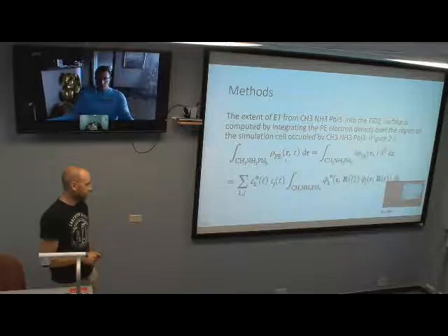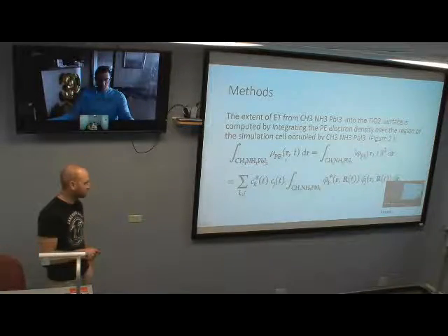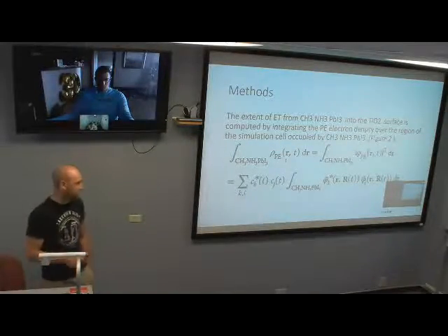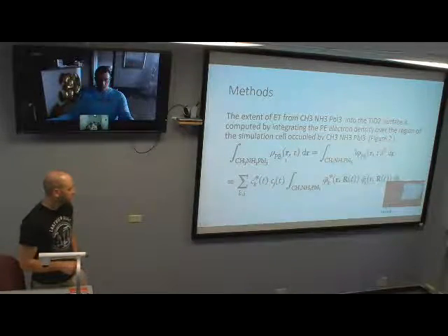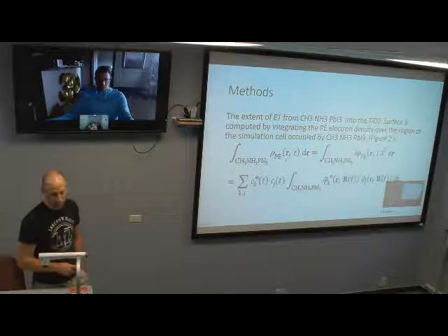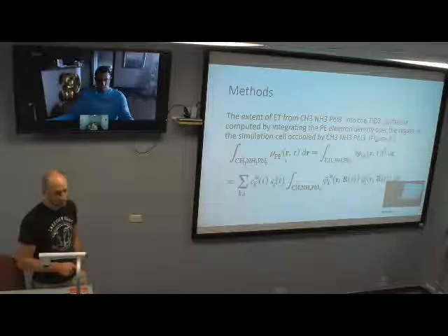So you want to integrate your electron density to figure out how much of the electron is on the perovskite. And then they just apply the previous formulas, which were written for this density as a square of the nonadiabatic wave function, constructed as a weight coefficient times Kohn-Sham adiabatic orbitals. And this is how you get to the last line in this equation.